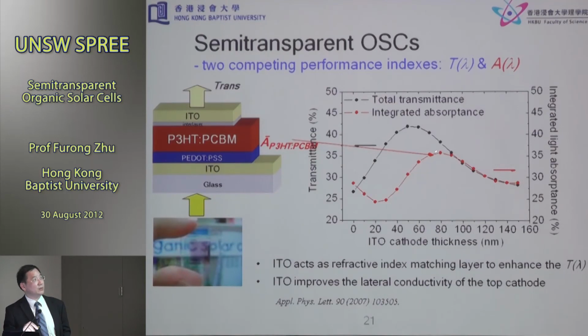So there's a maximum absorbance that could occur if the top ITO layer thickness is in the range of 70 to 80 nanometers. But we say that this is a semi-transparent unit. At the same time, we are also interested in looking at how transparent this can be. We are also looking at the transparency of the cells as a function of the ITO layer thickness, and it follows that way.